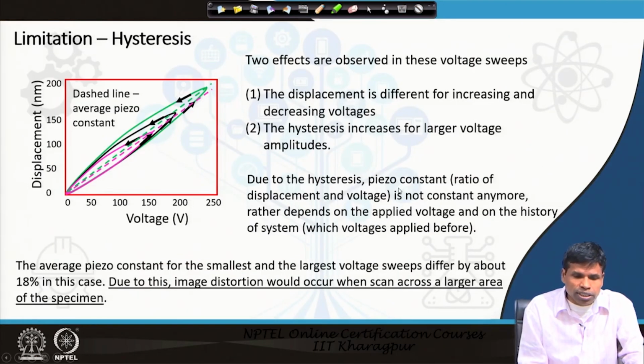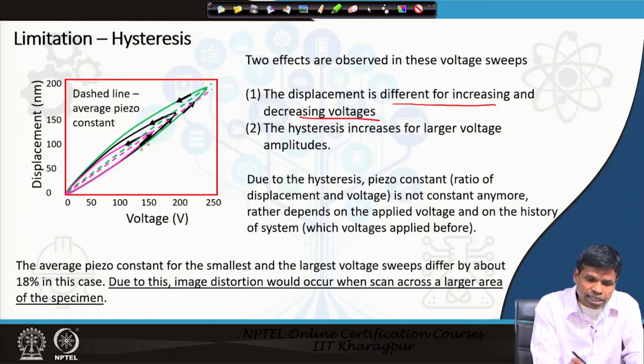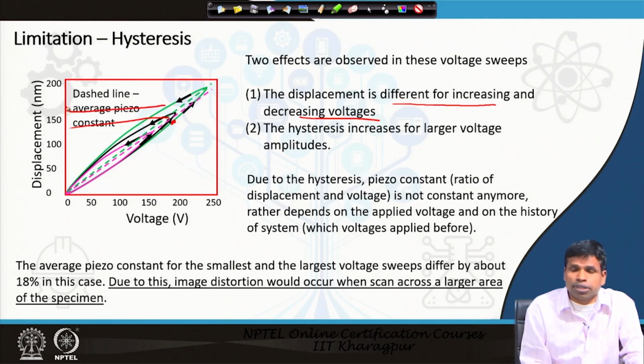So, this is what you see, a type of piezoelectric curve. The two effects are observed in this voltage sweep. One is the displacement is different for increasing and decreasing voltage. As we see, as we increase the voltage, the displacement goes up to a certain point here, and then when we are decreasing there is another displacement.